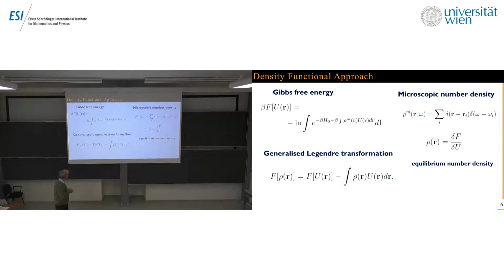But without this, we cannot develop any theory of any phase transition, because a phase transition between any two phases corresponds to a qualitative change of the equilibrium density, since the symmetry changes. So if we want the phase diagram, for example, of liquid crystals or of these rod-coil systems, we do need this free energy.